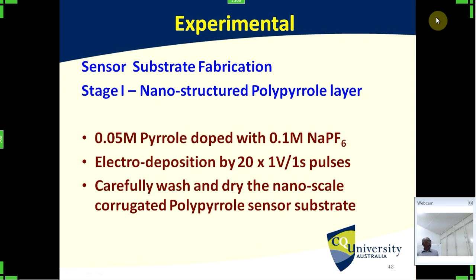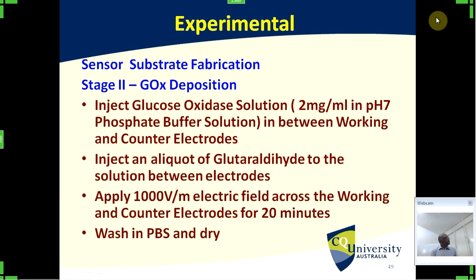The chemical compositions are like this, and we again fine-tuned this one. 20 x 1 volt, 1 second pulses gave us the best results, so we carried out the same set of experiments with this fabrication methodology. Then again, we applied a small amount of voltage across this 1 millimeter gap, and it gave us electrophoresis deposition of these two materials. And after that, we washed them in the PBS.